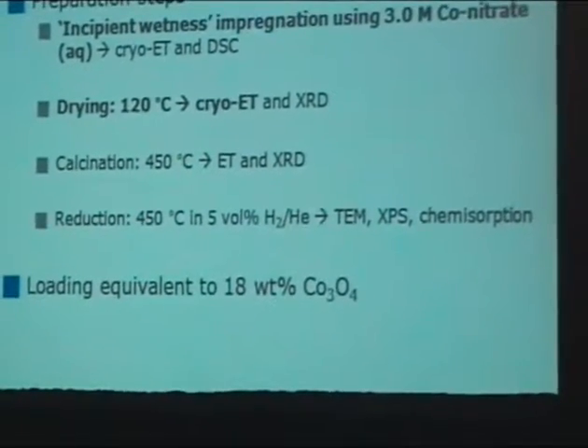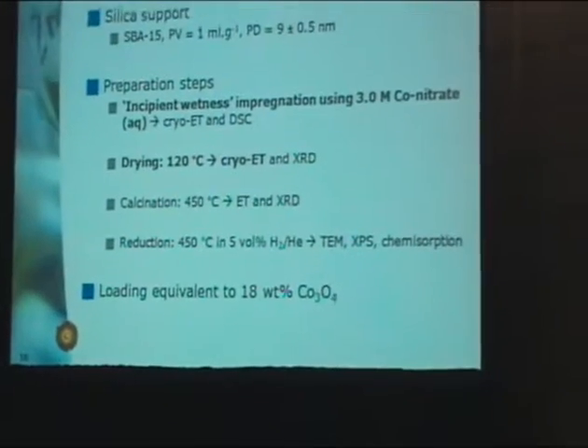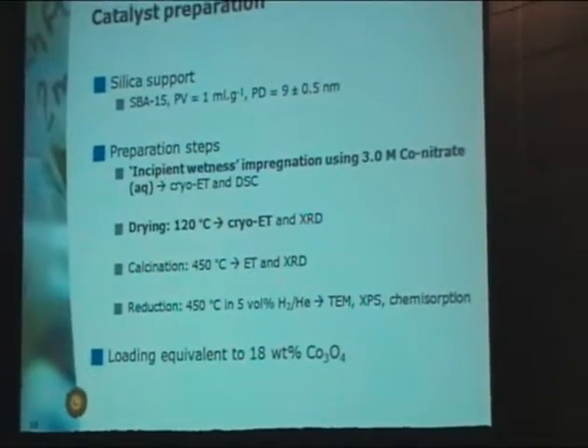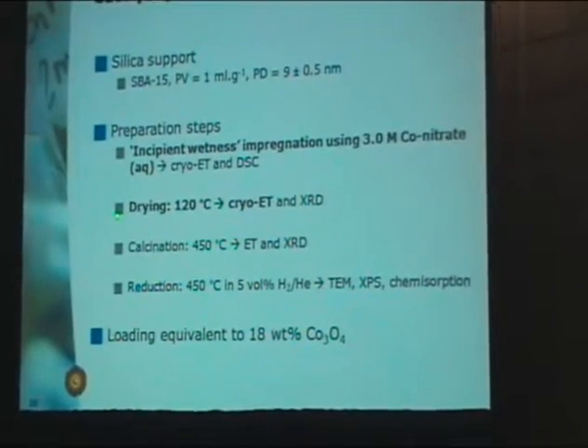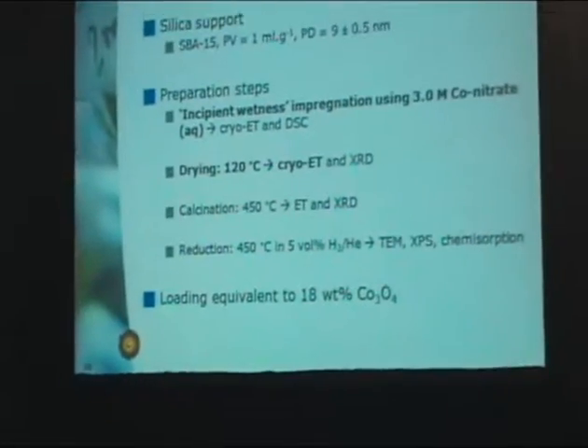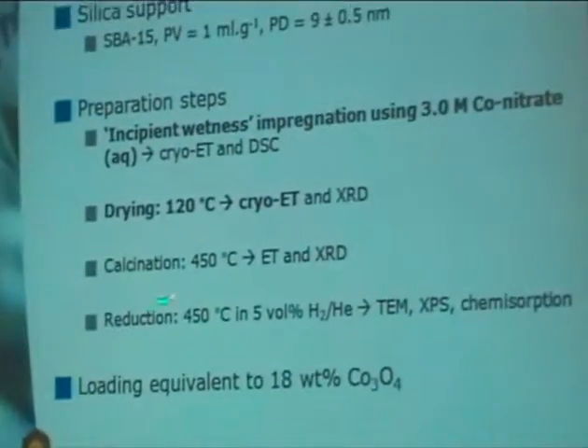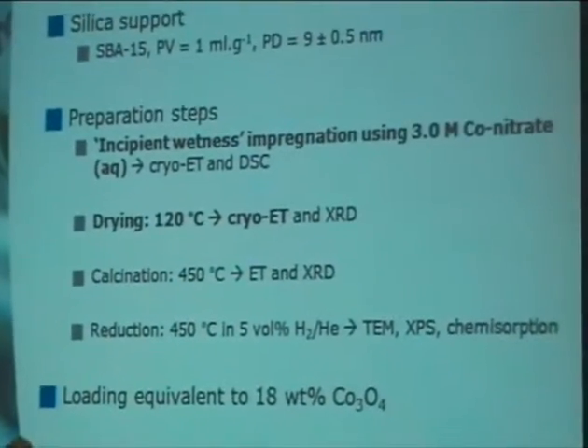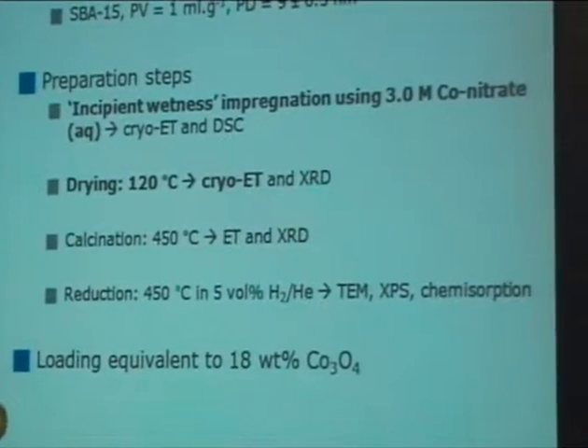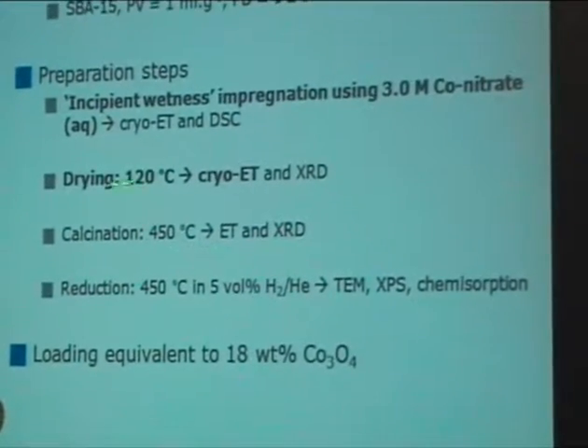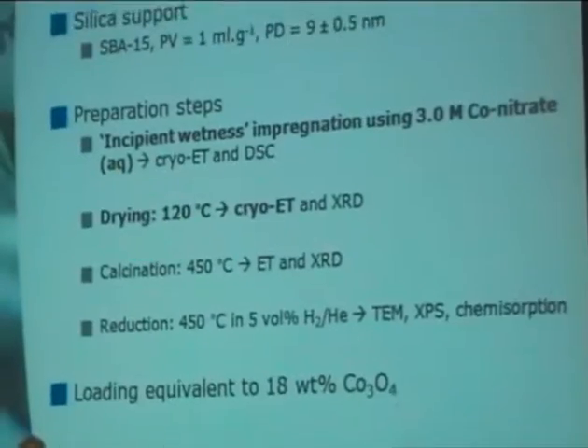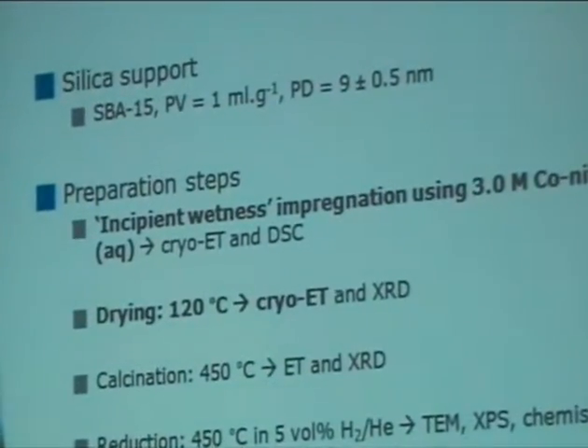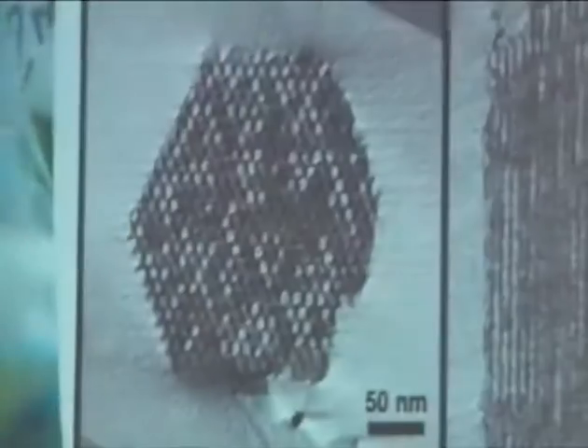We heard also about beam damage this morning. One way to prevent it is to cool your sample to 77 Kelvin in the electron microscope. And the dried sample we will study with electron tomography. So we will jump, and I will not go into these details. I will use another support for that, but just to highlight the impact of drying on the distribution of metal nanoparticles in supported catalysts. Here is the structure of the system.